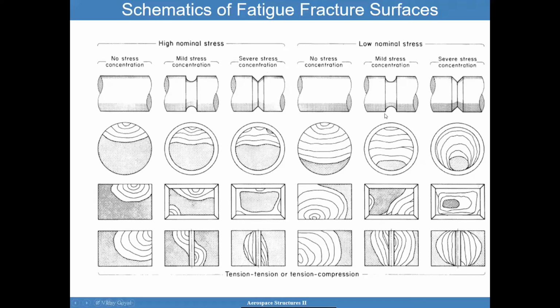because now this stress concentration accelerates the growth towards the periphery of that shaft. And then you're going to have a smaller net section failure area. If I have a severe stress concentration, then it's going to be even more dramatic with beach marks. They're going to look like it initiated here but didn't. It's just that the initial failure is not as visible, but you still get beach marks until you have a final fracture.